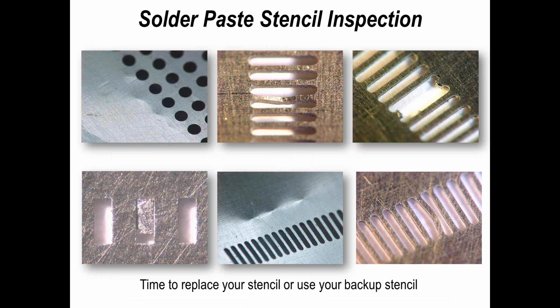But you can see they're either coined, that's deflected away from the print area. The separator parts are deformed or broken. And in the one case on the bottom left, you can actually see a laser cut stencil where part of the aperture is still actually in the stencil. Not a very good example of quality control from the manufacturer.